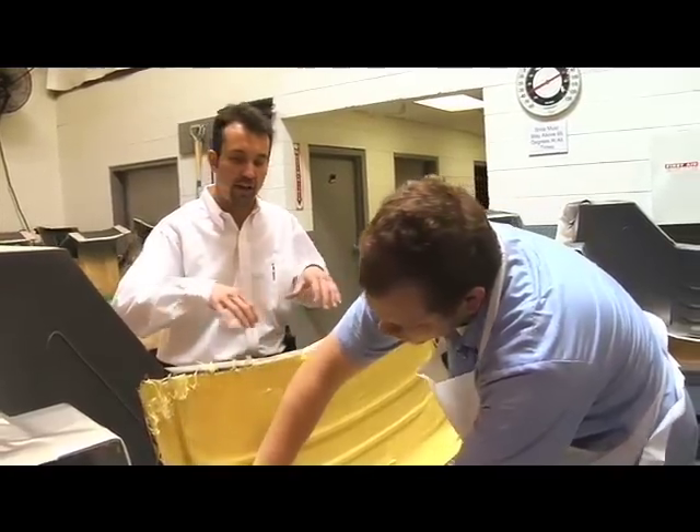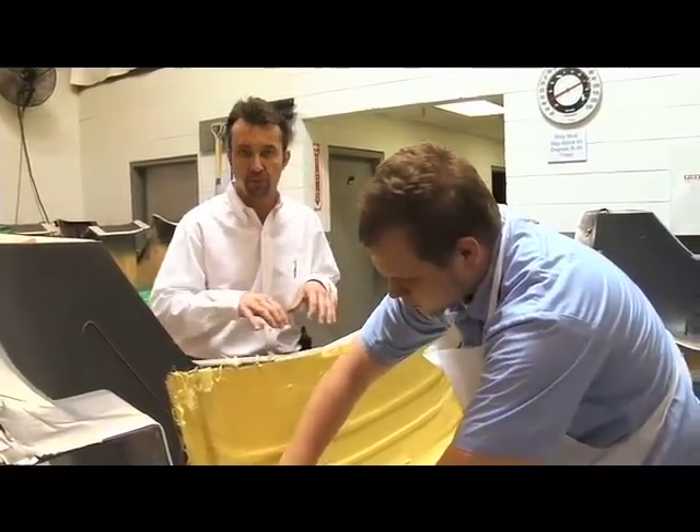Now what James is doing right now — he's actually pressing the materials in after it's been impregnated with all the epoxy resins and making sure that it's in every nook and cranny in the mold, reducing any types of air voids by eliminating bridging, so he's working the material into all the grooves and cracks.